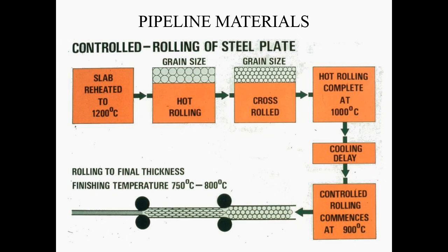So we start with a steel slab, about this thick, as I said, at least 150 millimetres thick, 6 inches in old money. The slab is reheated to 1200 degrees C, so furnace treatment. How long do we have to heat it? Well, we have to make sure that the whole slab is heated, so there's a certain soaking time that you need to put on. Then it goes through hot roll systems. And I've done a cartoon of the grains here. So individual grains are approximately spherical. The steel's made up of individual crystallites with different orientations. The grains are quite large because at high temperature the grains tend to grow.